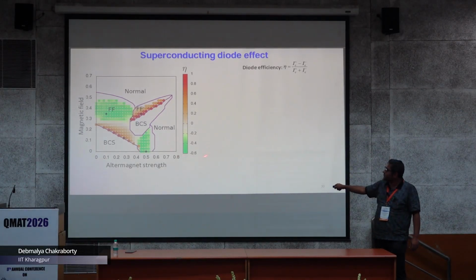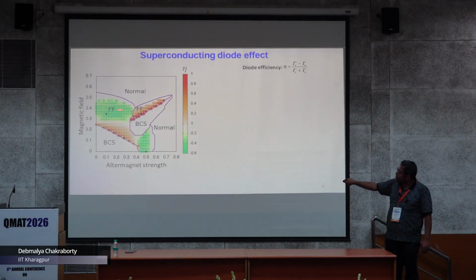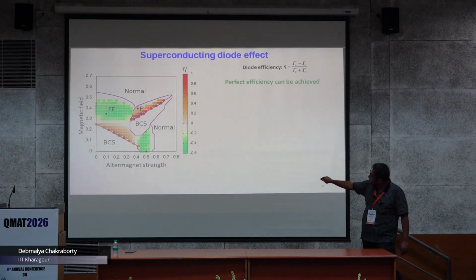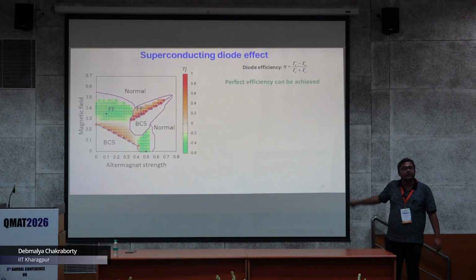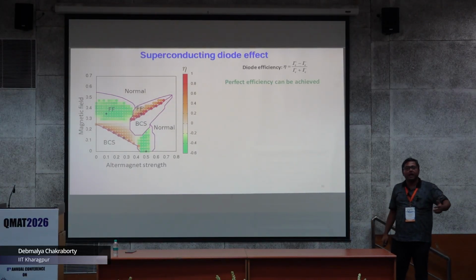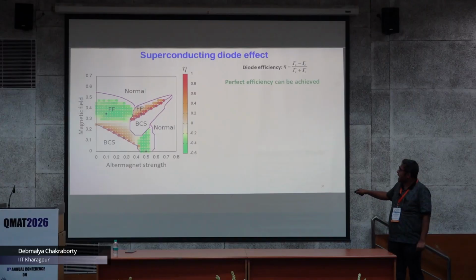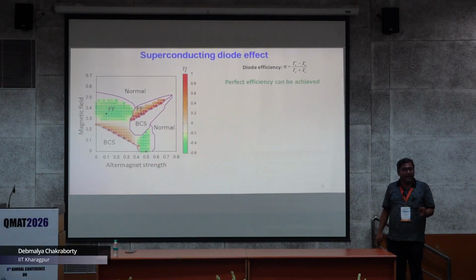You get efficiency of the order of 60% to almost 100%. That means if you look at these regions, these are almost 60% efficiency. And interestingly, you see that these regions have almost perfect efficiency. By perfect efficiency, I mean that you have a diode efficiency of almost 100%. And this is not a miracle.